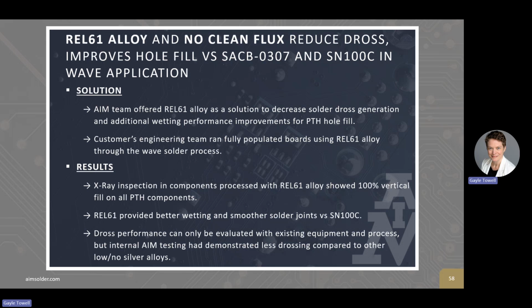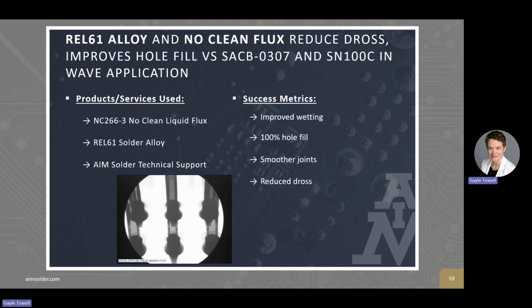The results, X-ray inspection of the components processed with REL61 showed 100% vertical fill on all of the components. It provided better wetting and smoother joints than what they got with the SN100C. And dross was not specifically measured, but it appeared to dross less than the other alloys. So they had improved wetting, 100% hole fill, smoother joints, and reduced dross.